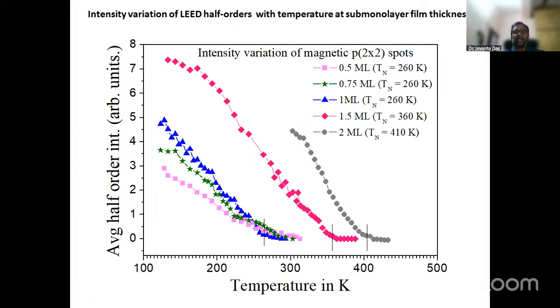And a beautiful thing happens when we go below the monolayer range. Within the submonolayer range, we find that the Néel temperature does not decrease that much. However, there is an intensity variation at lower temperature. As I said, below 1 monolayer and also at 1 monolayer, I had to cool down the sample with liquid nitrogen to observe the half-order spot. So you can see that while we are cooling down, we can find some intensities, and the variation of the half-order intensity is there. It depends most probably on the domain size of the nickel oxide film.